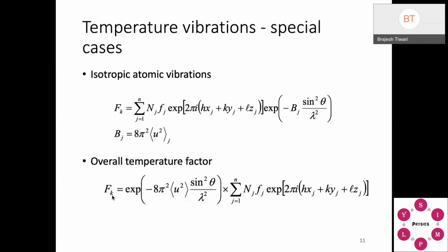Usually you may have seen in X-ray diffraction that the peaks at lower angle are very sharp, and if you go to peaks at larger 2 theta value, the peaks become broader. So if you are directly utilizing the Scherrer formula for calculating the particle size and have not taken this factor into account, you may end up getting the wrong particle size or crystallite size.